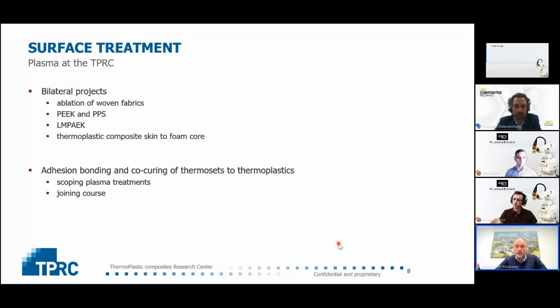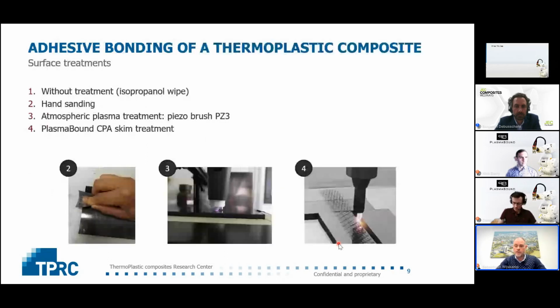Also, we have been developing a 2-day course on joining, where next to fusion bonding, welding of thermoplastics, which is a very important topic these days with thermoplastics, we also work on adhesive bonding, for example, combined with plasma treatment. So that's where I will show a bit of our scoping study. So we looked at 4 treatments: without treatment or just a small isopropanol alcohol wipe, hand sanding, atmospheric plasma treatment, just with a little pen-sized plasma, Piezobrush PZ3, all done manually, and the Plasmabound CPA skim treatment, as Nick showed earlier.